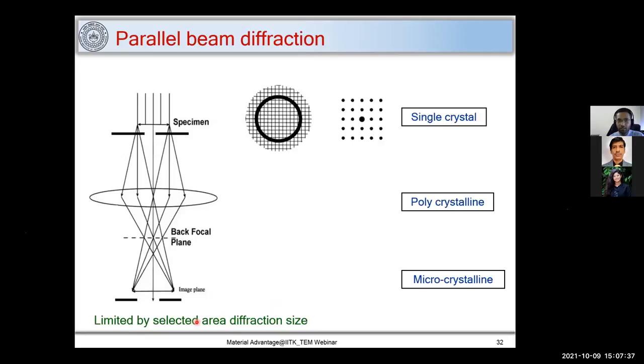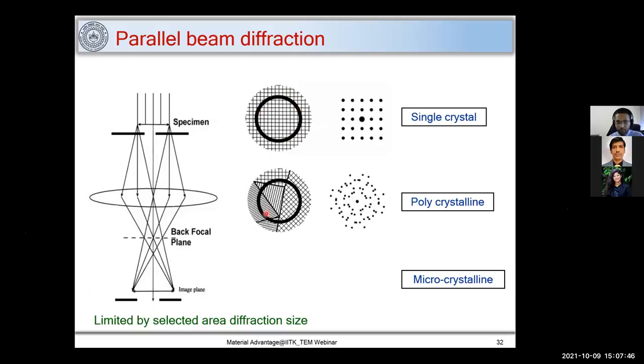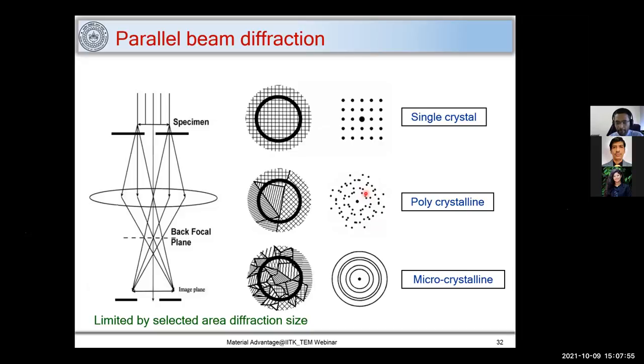So let's say we have a single crystal. So we get a spotty pattern like this, and this is a selected area aperture which we are using. If there are 2-3 grains or a polycrystal material, you get a diffraction pattern like this, which is not continuous but a spotty pattern. And here you have many grains, and we get this kind of a ring pattern in the case of microcrystalline material. So based on aperture size, you can have these kinds of diffraction patterns from a material.